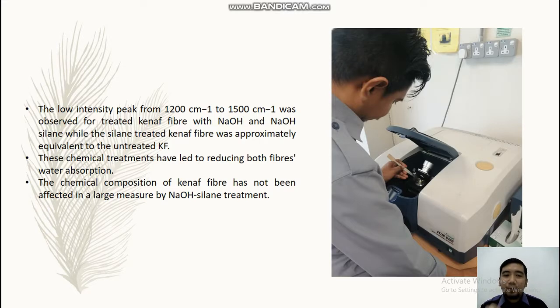Okay, the low intensity peak from 1,200 to 1,500 was observed for treated Kenaf fiber with NaOH and NaOH silane, while the silane treated Kenaf fiber was approximately equivalent to the untreated Kenaf fiber. This chemical treatment has led to reducing fiber water absorption. The chemical composition of Kenaf fiber has not been affected in large measure by NaOH and silane treatment.